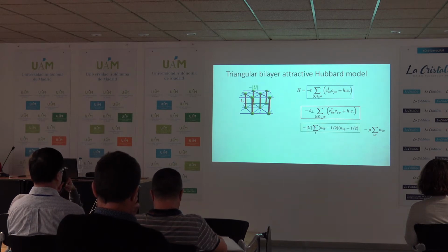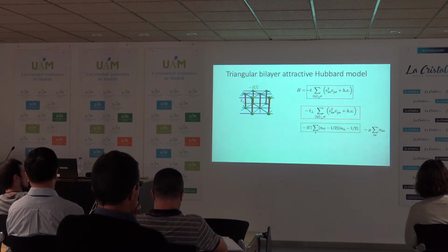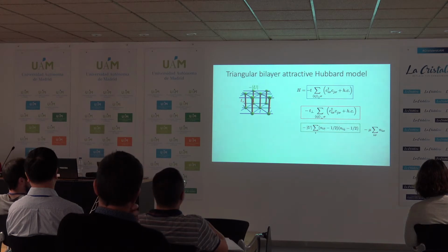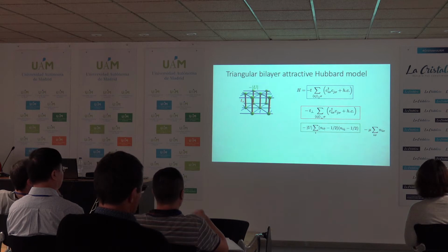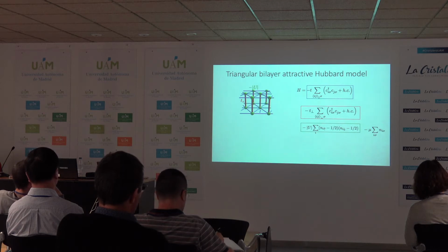So either you can take a single layer with 2 atoms per unit cell or 2 orbitals per unit cell. Here I've just taken 2 layers. And the reason I've picked a triangle rather than a square is just because I want to avoid any other competing orders like charge density wave and so on. You can't do that in an experiment, you get what you get, but we can control this in our model.